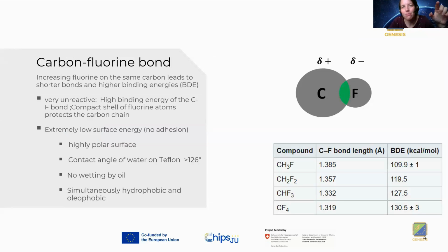You can even see a proof of that by looking at the table. You can see different compounds. In the first row, this compound has 1 F, then the second row 2 F, then 3 and 4 at the end. If you compare the length of the bond between the carbon and the fluorine, you can see that it starts with 1.385 angstrom. If you take a look at the last line, it is reduced to 1.319 angstrom. That has to do with the amount of fluorine.